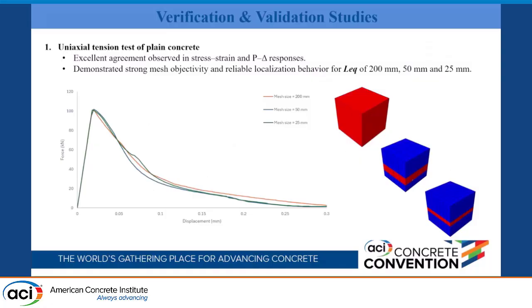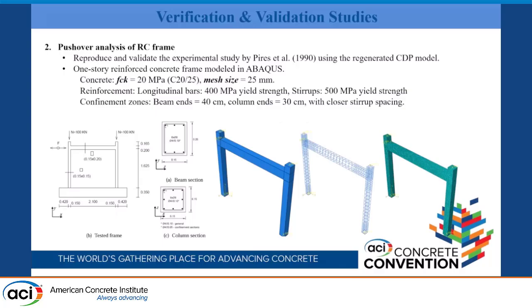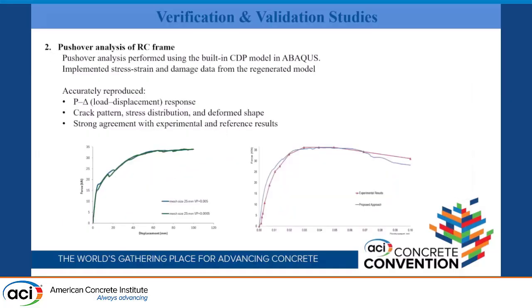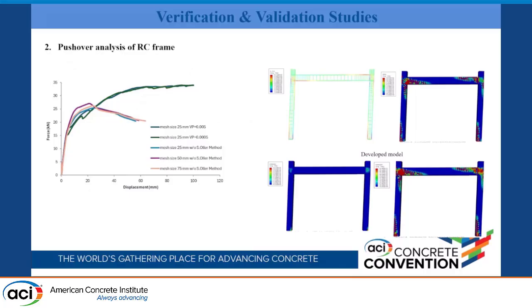As you can see, we have solved the mesh dependency problem. I'm not showing the negative results here, but without the fix, the post-peak response will soften indefinitely. The more you refine, the softer it becomes. It almost collapses back onto the backbone curve. This is the pushover analysis. This is the calibration. Experimental measurements are on the right-hand side, and our model analysis on the left-hand side for different mesh sizes, with and without the use of this consistent regularization scheme we got from Alfaro. If we don't use it, it doesn't work. If we use it, it does work.